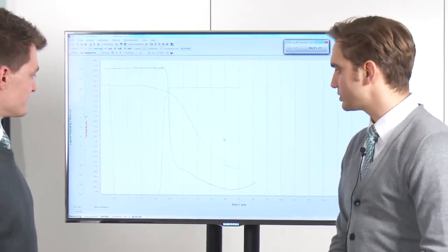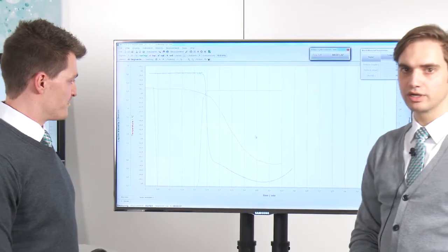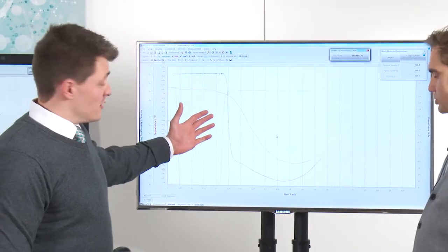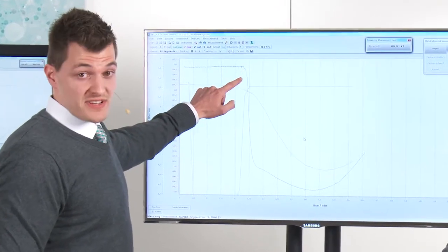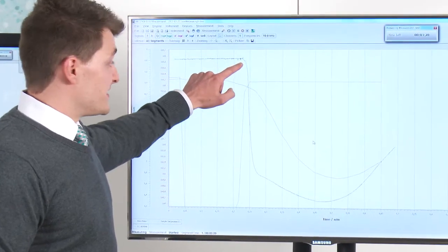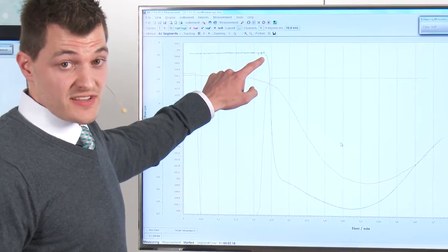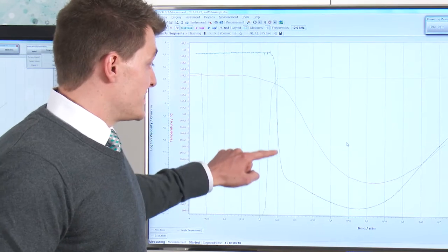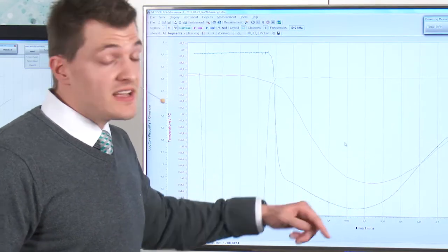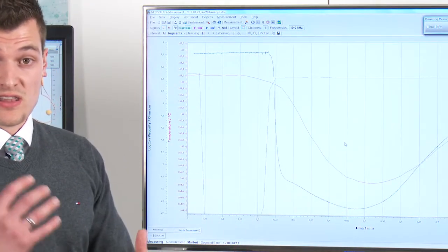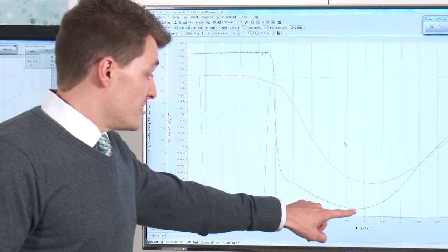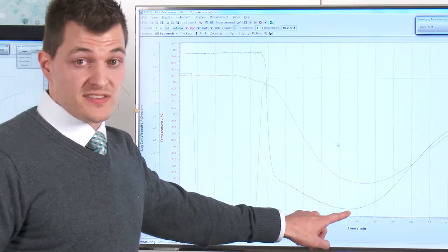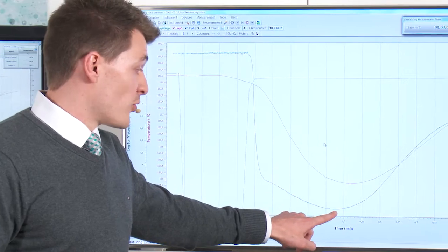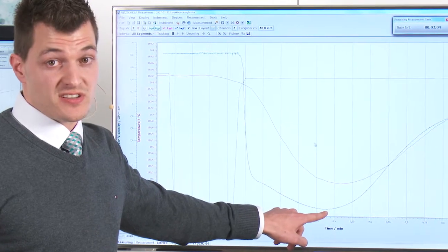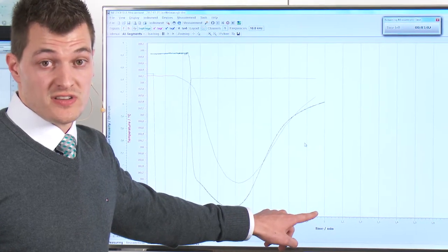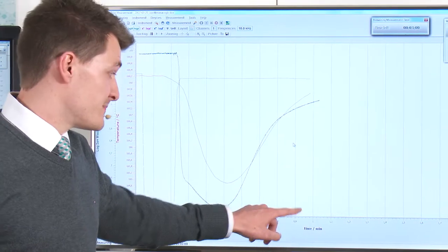Yeah, Alex, just tell us what is happening with the DEA here. What can the DEA show us? What you can see here is a very sharp decrease in ion viscosity. This indicates that the sample has just arrived at the sensor surface. Then you can see a very sharp decrease that indicates that the material is getting less viscous. So here you can see a minimum. This is the point where you've reached the lowest ion viscosity that correlates to the state of the lowest viscosity you know from rheology results.